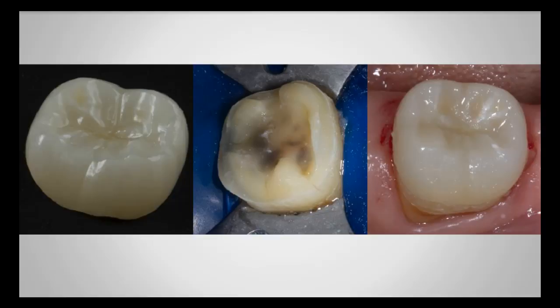We have a coating on the dentin, so the dentin's sealed and protected. I take my air abrader and I just make a quick poof across that surface to clean it. You don't want to blast, because depending on how thick your immediate dentin sealing base is, you don't want to blast away the flowable that's there. So we just do a very light clean. I use the 28 micron silica with their fine tip on the Danville air abrader, and it makes a very